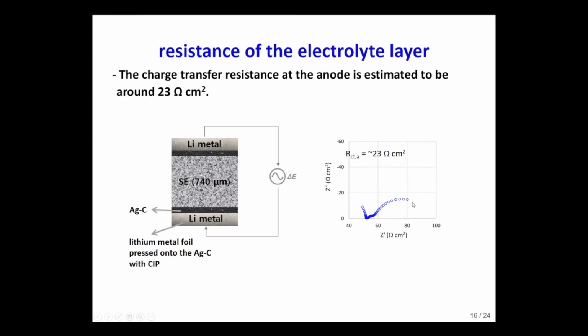If we look at the Nyquist plot, although the presence of a small semicircle indicates that the process is more complicated than expected, we could reach the conclusion that the overall charge transfer resistance could be about 20 ohms per centimeter in this way.